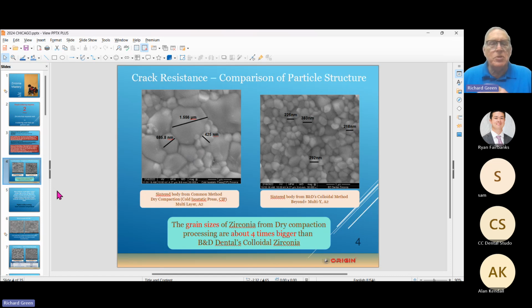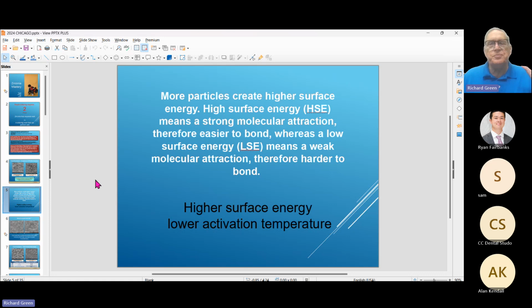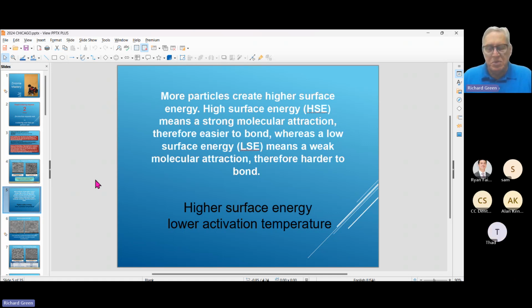When you talk about creating more grains in the zirconia, part of why you want more grains, why you want nano, is that more particles create higher surface energy. Higher surface energy means strong molecular attraction. We talked about that in the beginning. The stronger the molecular attraction, the easier it is to create bonds. Whereas a low surface energy, because you get different size particles and they're much larger, means a weak molecular bond, therefore harder to create a bond. High surface energy also means a lower activation temperature.